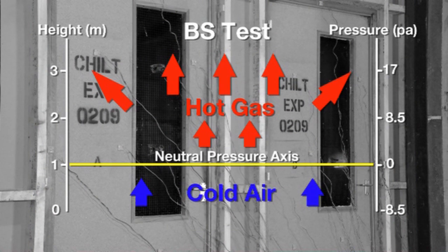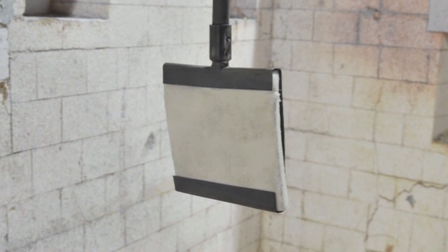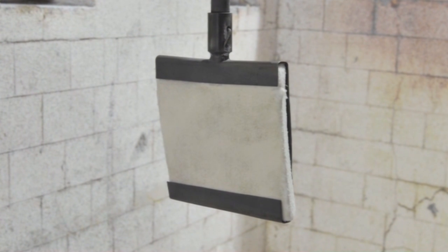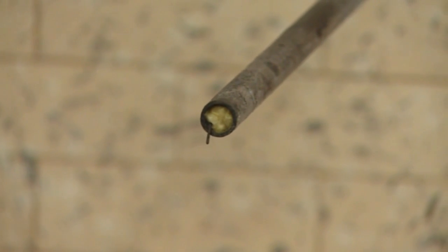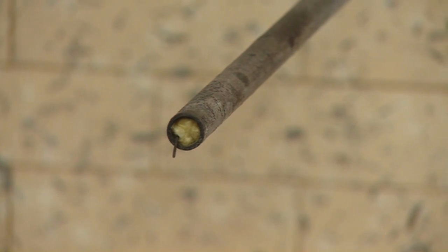At a set distance above the threshold, a neutral point is specified, where the furnace pressure is the same as the laboratory pressure. Both negative and positive pressures can contribute to the failure of a test specimen. It is in the type of thermocouple which measures the furnace temperature and in the specified pressure regime that the British and European tests primarily differ.